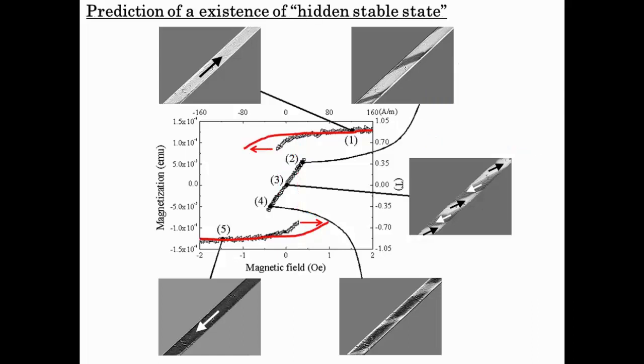If we control the property like this, the element magnetization property is limited between two states, single domain with positive direction and single domain with negative direction. Based on our numerical simulation, there exists a multi-domain state, and the magnetic energy of this state is lower, and it's a stable state.